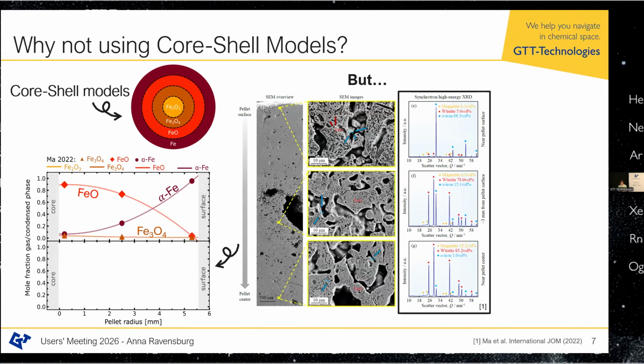If I plot this now, you have the pellet radius on the x-axis, and you have the phase composition on the y-axis, then it would look somehow like this. I only have 3 points, it's quite difficult to plot, but this is how it would look. If I would try to represent this in a core shell model, it would look more like this. There can only be one phase present at the same point in the location, and this does not really represent the actual structure that I observe in experiments.